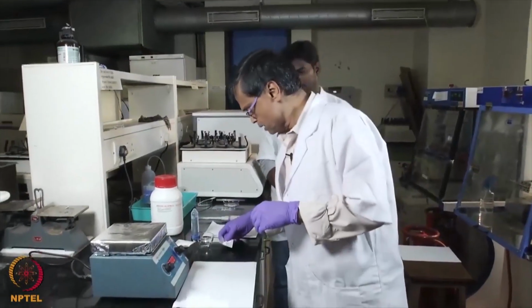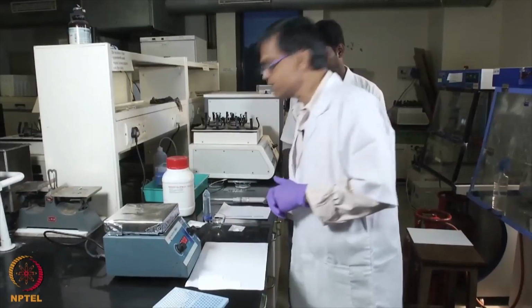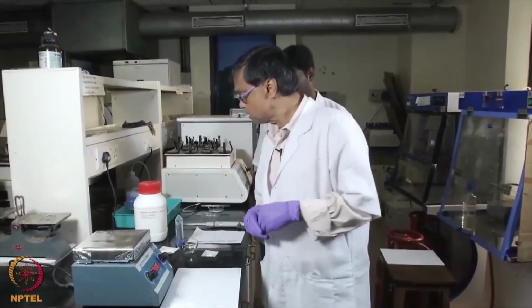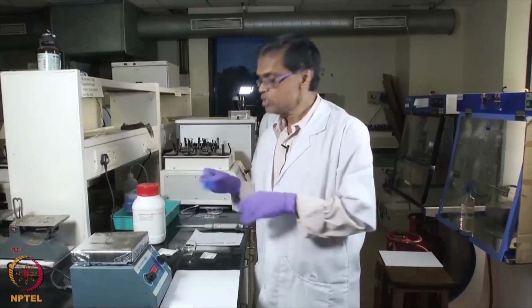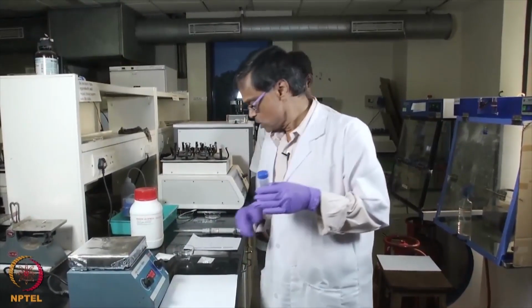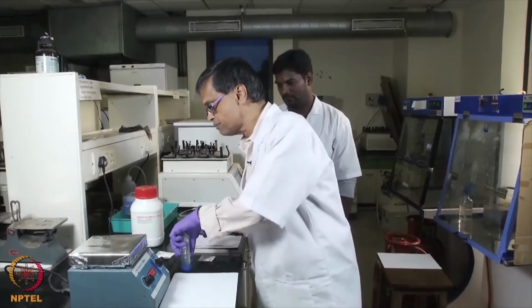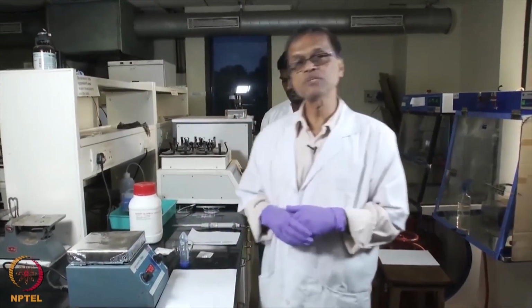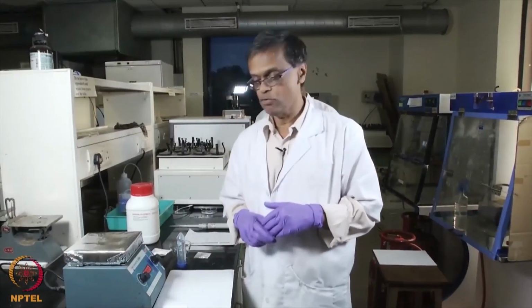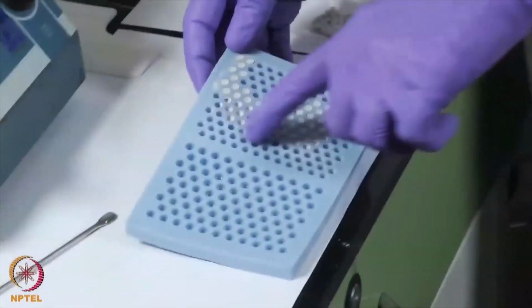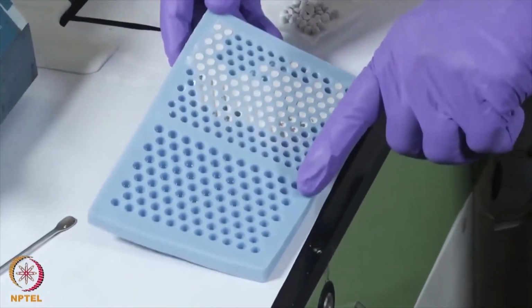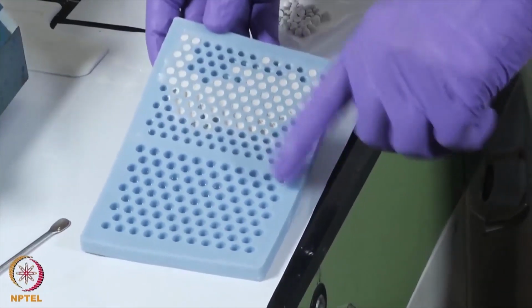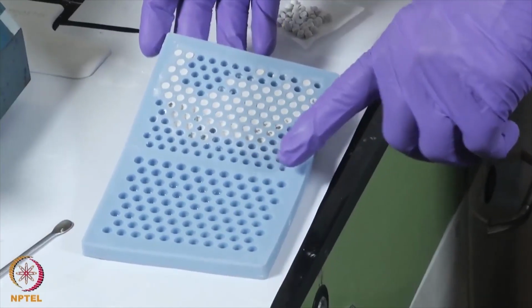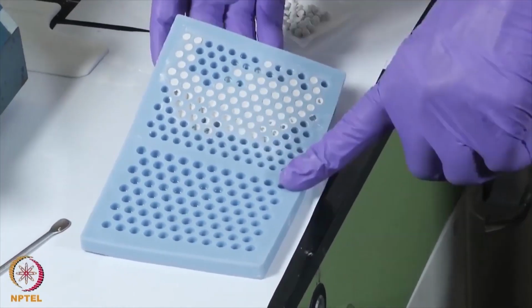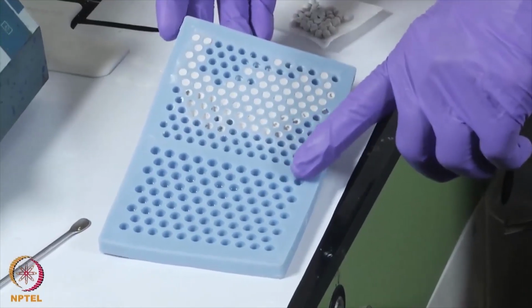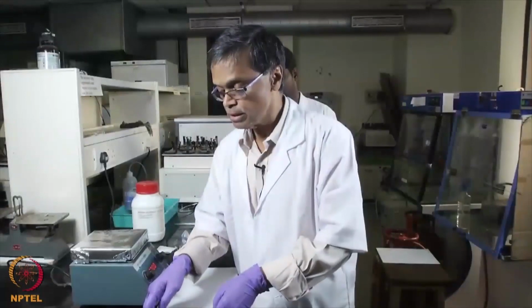formation. So you need around 700 microliter of water for about 1 gram of calcium sulfate. You need to use ultra pure water here. So I have taken 5 times. That means I have taken 5 grams of calcium sulfate and 3.5 ml of ultra pure water, because look at these molds. Here we can make 4 mm beads, here we can make 5 mm beads. So if you want to cover as much area, then you need to correspondingly take the same ratio. So for 1 gram of calcium sulfate, we need 700 microliter of ultra pure water.